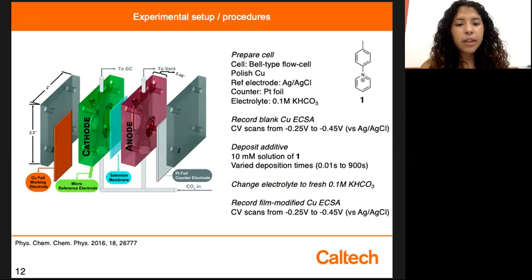Our experimental setup and procedure consisted of mimicking how we would normally conduct CO2 reduction, but we modified the procedure by recording the ECSA of a blank copper electrode and then depositing a 10 millimolar solution of pyridinium. I varied deposition times ranging from 10 milliseconds to 15 minutes. Then we changed the electrolyte to a fresh batch, recorded the film-modified ECSA, and then conducted CO2 reduction.